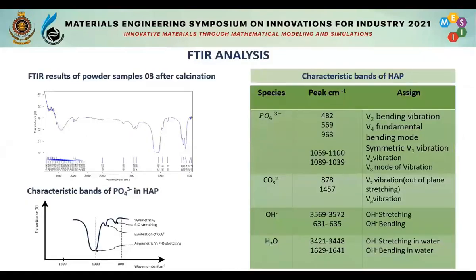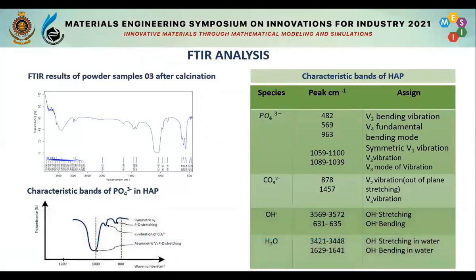In the FTIR analysis, we have seen all the characteristic bands for hydroxyapatite, which confirmed the formed crystalline hydroxyapatite. There is also some carbonate incorporation in the crystal structure, but it is not harmful to biological hydroxyapatite, because naturally available materials in our hard tissue also have some carbonate incorporation. We assume that the carbonate comes from atmospheric carbon dioxide